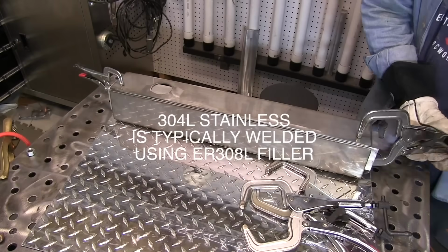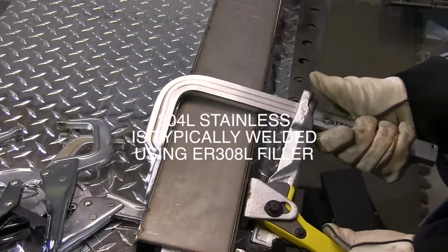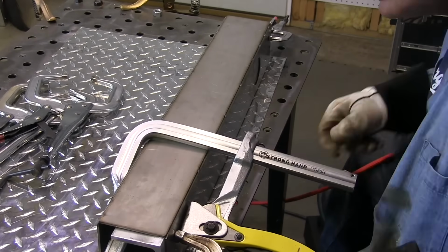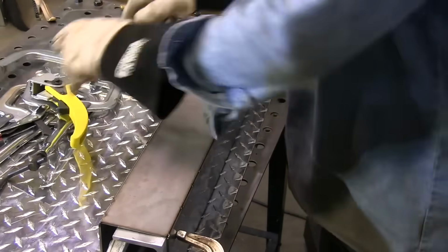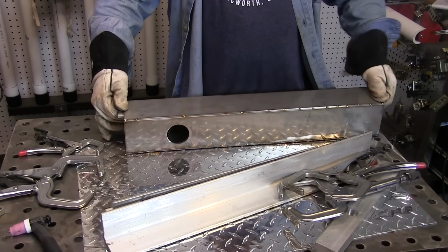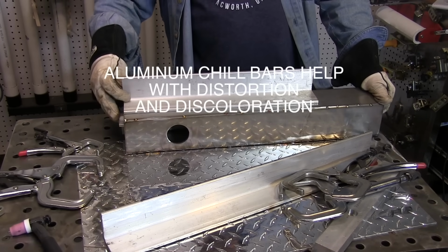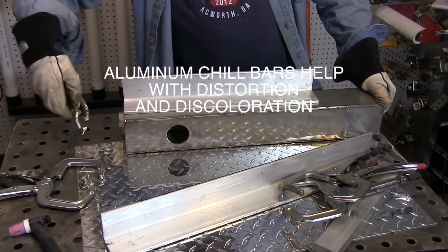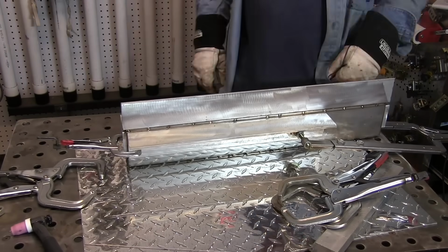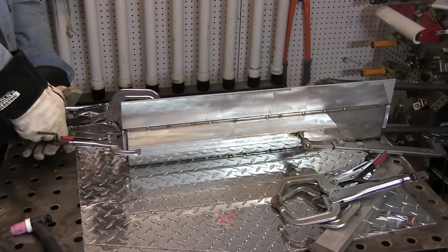One of the main things to consider when you're TIG welding stainless steel is maintaining the stainless properties. And the way you do that, you don't use any other wire brushes other than stainless steel wire brushes that have only been used on stainless steel, and you limit your heat input, and chill bars can help an awful lot with discoloration as well as distortion.